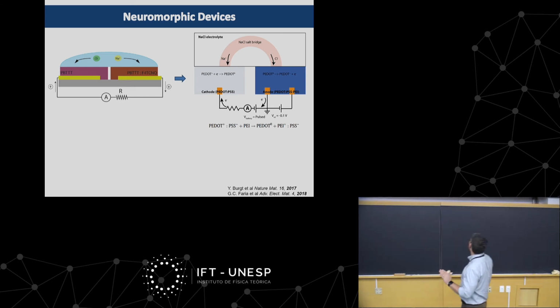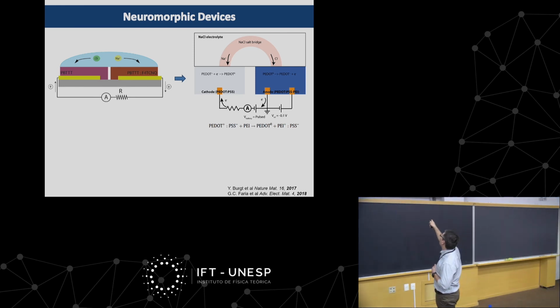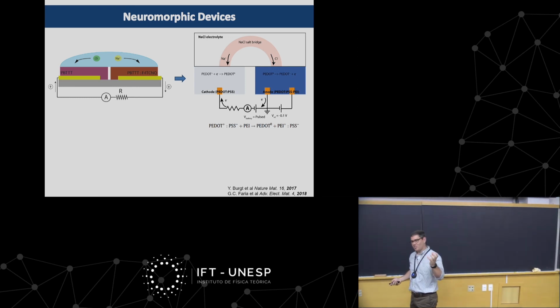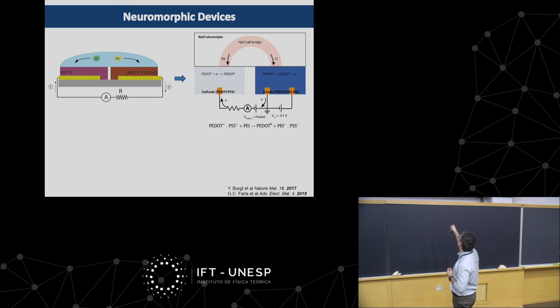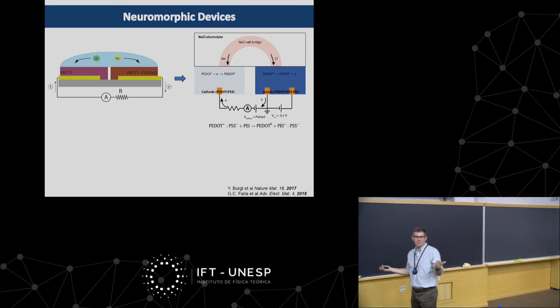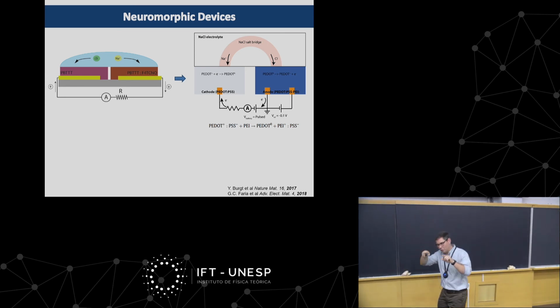And therefore, I can open this anode to discharge, and ions or charges move to this electrode, and therefore fewer charges are in this material, right? If I keep measuring the conductivity of this electrode as the charges are discharged, I'm going to see a change in conductivity on that particular electrode. I can put a switch here and open and close it at different times, and therefore I'm going to reduce the conductivity. As I open that switch, the conductivity is maintained, so I have a new level of memory.